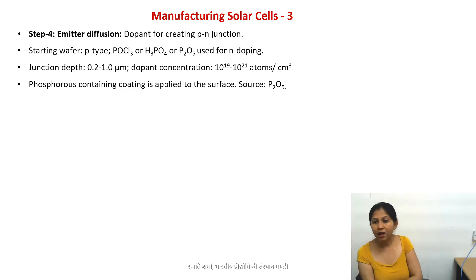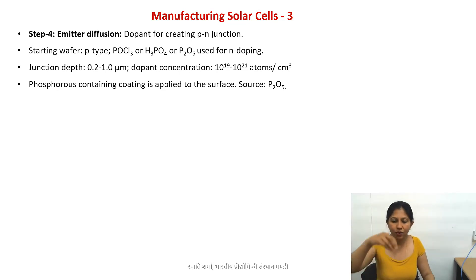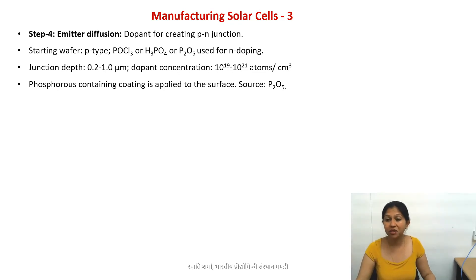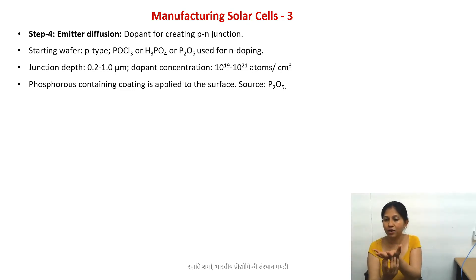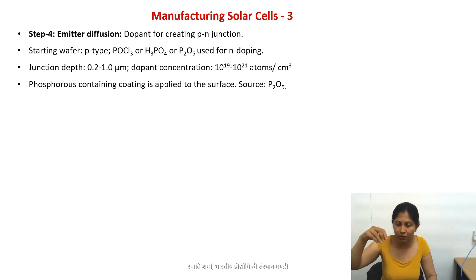So what we do is take this P2O5 or POCl3 and do spin coating. What is spin coating? You take a couple of milliliters of solution, place it on top of your wafer, and spin the wafer at around 3000 RPM — very high speeds. The wafer is attached by vacuum to a holder so it does not fall and can spin at very high rotation speeds. This process spreads the paste or liquid completely over your wafer.